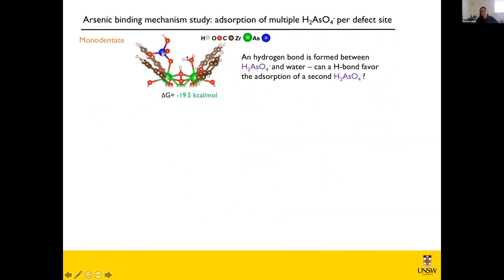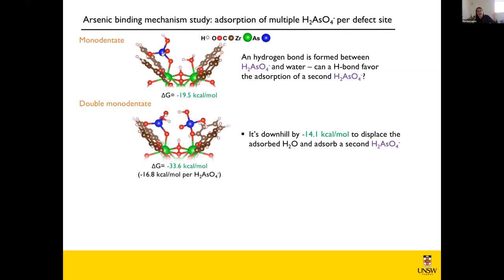And so we wondered whether we could use a similar hydrogen bond to stabilize two arsenic species at once, because that would be amazing for adsorption performance if, given one site, we can get two arsenic trapped instead of one. And so we were really happy to see that this actually can happen, and it's favorable by 14 kcal per mole to kick out this water molecule and place there a second arsenic species.